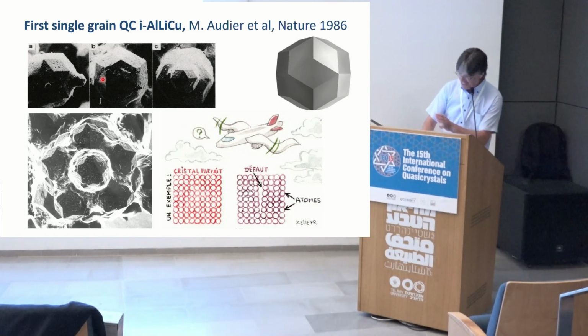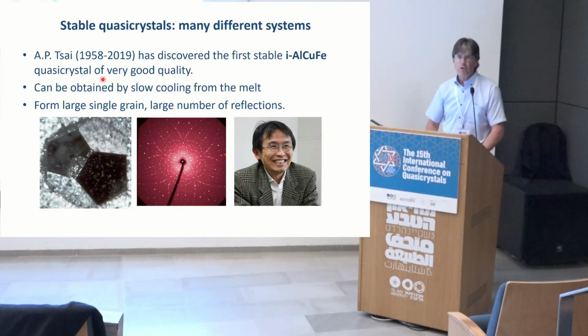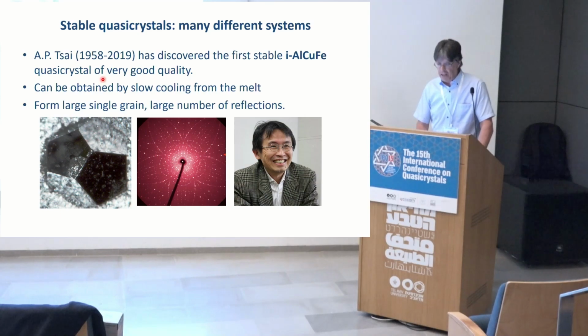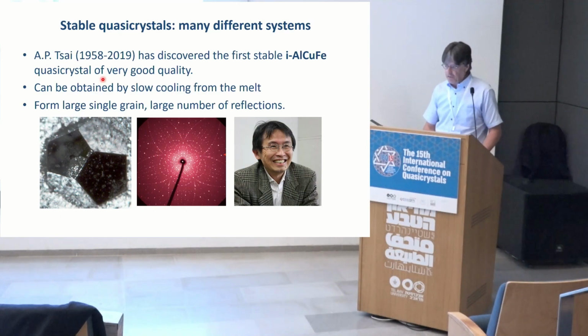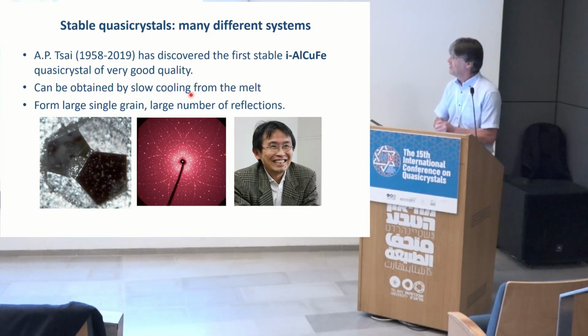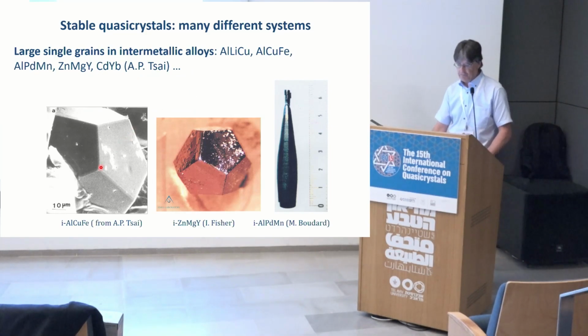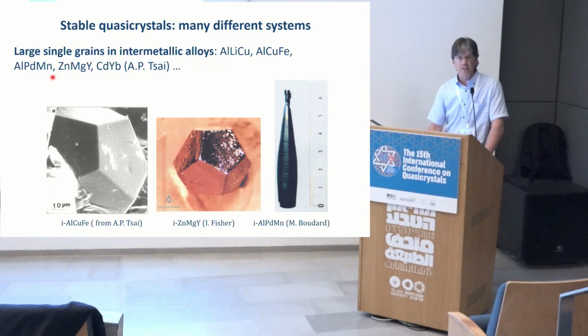So one indirect application. But most of the stable quasicrystals were discovered by An-Pang Tsai, who discovered the first stable aluminum copper iron and a whole series of intermetallic compounds that can be obtained from the melt, cooling slowly, and exactly in the same way you would obtain a periodic crystal. So that was really a breakthrough, because we had now single crystals with a large number of reflections and extremely high quality. I'm just showing a few: aluminum, lithium, copper, iron, aluminum, palladium, manganese, zinc-based material, cadmium-based, I will come back later.